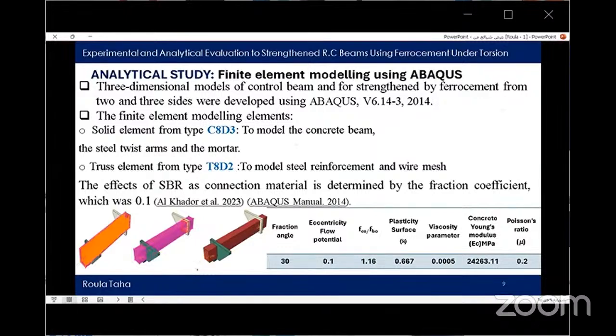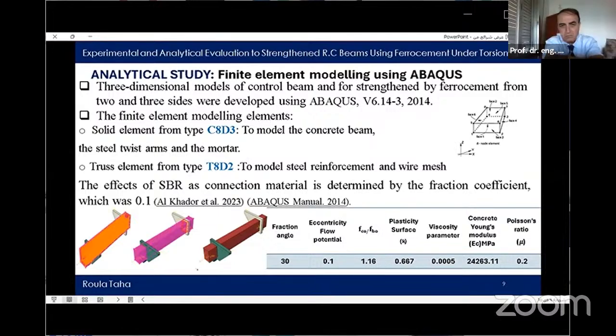The analytical study. 3-dimensional models of control and strengthened beams by ferrocement from 3 and 2 sides were modeled using Abaqus version 6.14. We used the element C3D8, which is defined by 8 nodes having 3 degrees of freedom at each node, to model the concrete beam, steel twist arms, and mortar. While we used the element T3D2, which is defined by 2 nodes with 3 degrees of freedom at each node, to model reinforcement and wire mesh.